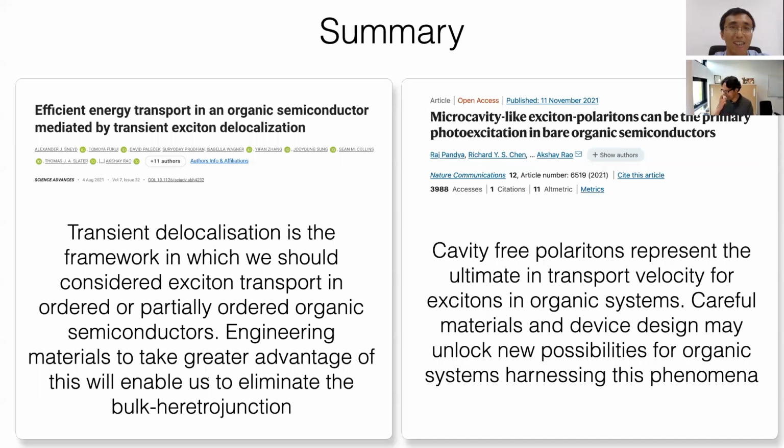Yeah, I think so. Essentially, the question is asking more about the photostability of materials. The classic challenge in photostability is blue OLEDs. Many of you will know that, as a field, we have struggled with blue OLEDs for more than 20 years. The problem, which is in some ways the same in OPV and OFETs, is that high energy excitons fuse together and then they cleave the carbon-carbon bonds, or whatever bonds are in the system.